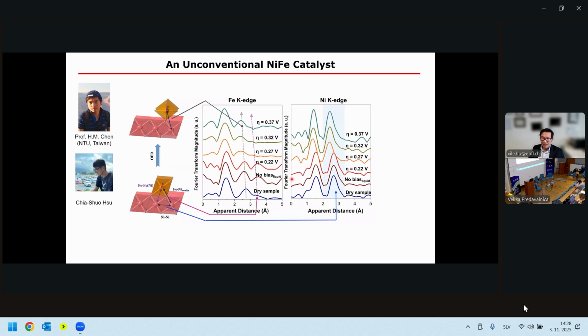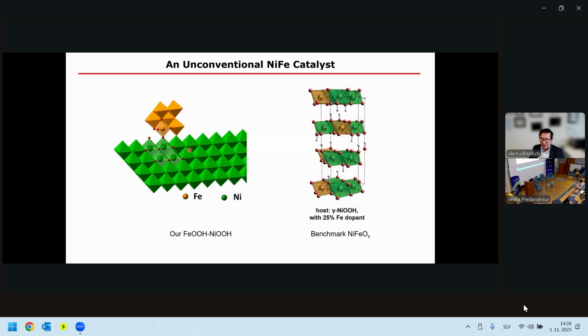We have studied the active structure of the catalyst using operando X-ray absorption spectroscopy. We are in collaboration with a group in Taiwan. We look at iron K-edge or nickel K-edge. We also look at XAFS and so on. And we know under OER conditions, our catalyst is basically two components: an iron oxide cluster in a core-shell arrangement on a nickel oxyhydroxide support. This structure, I will draw it again here, is quite unique because we have a bicomponent catalyst. This is different from the classic nickel iron catalyst, which is basically iron doped into layers of gamma nickel OOH structure. And we think this structure gives some edge in activity, which can be understood by DFT calculations.